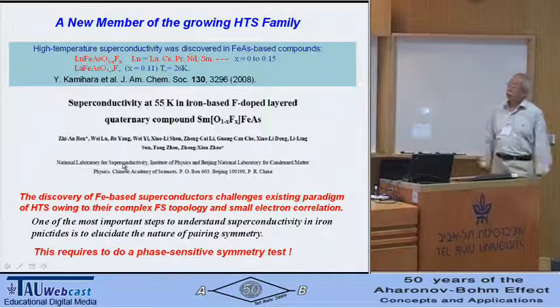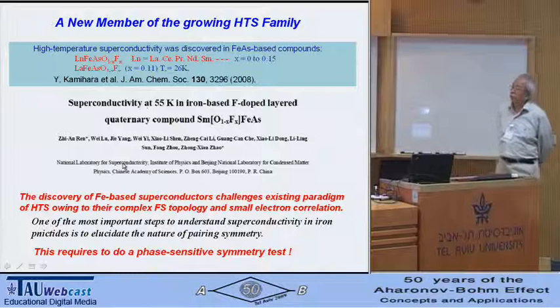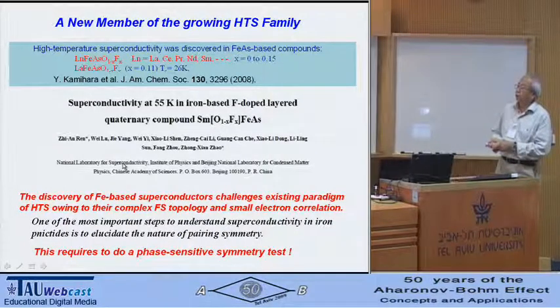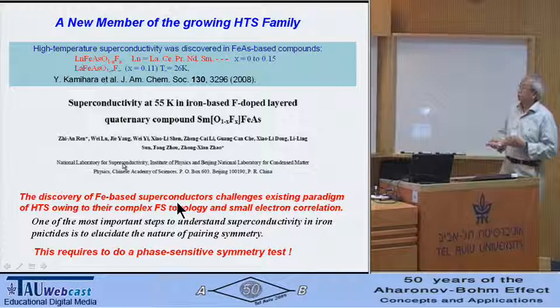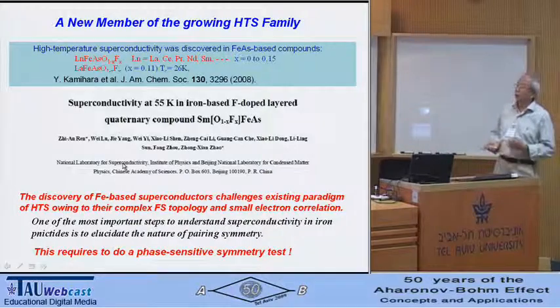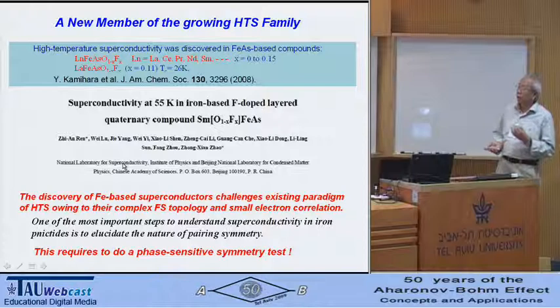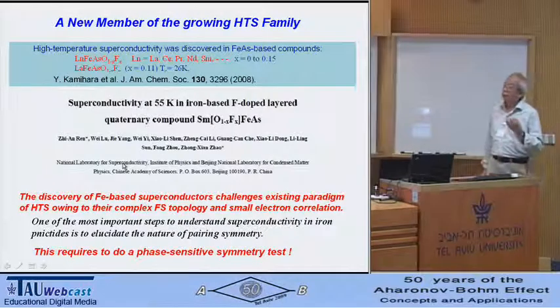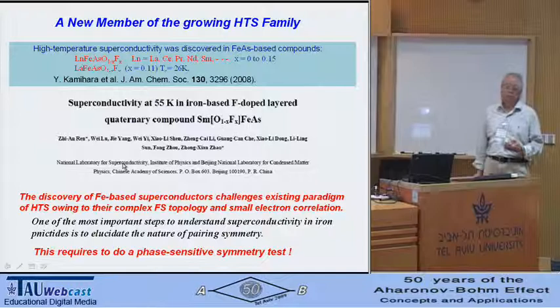So this remarkable discovery of high temperature superconductivity in iron-based superconductors really challenges the existing paradigm of high temperature superconductivity. That is because they are characterized by complex Fermi surface topology and a small electron correlation, unlike the cuprate superconductors.